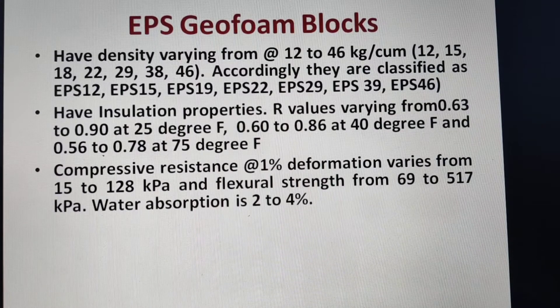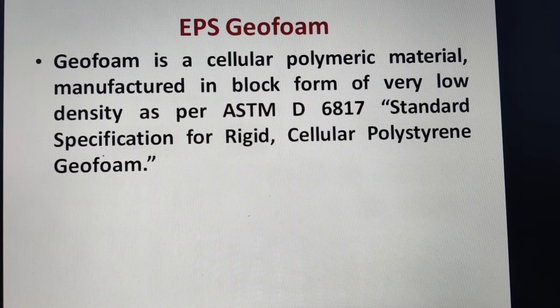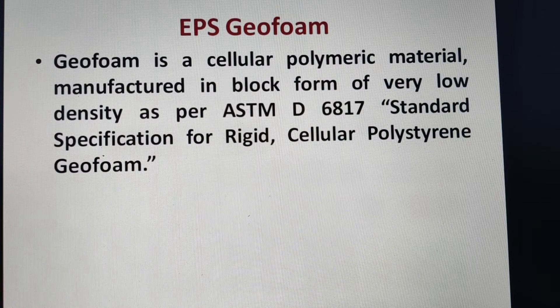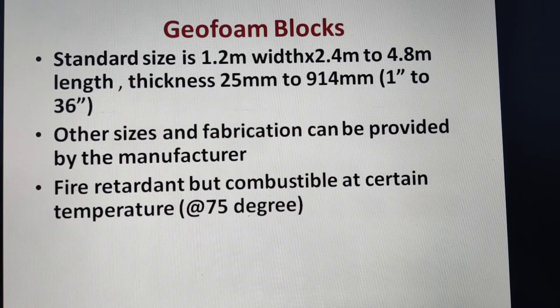Water absorption is also very low — 4% for EPS 12 down to 2% for EPS 46. EPS geofoam refers to cellular polymeric material manufactured in block form at very low density, as discussed, conforming to ASTM D6817.